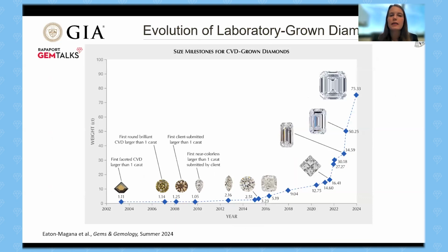Now, in the past couple of decades, there's been a huge evolution in the quality and the sizes and the quantity of laboratory-grown diamonds. So here we have an example of the CVD-grown diamonds. And back in the early 2000s, most of the material was really brown, small, not necessarily the most valuable within the gem trade. But as they have perfected their growth procedures, they have also introduced post-growth treatments. We have seen a huge increase in both the size and the quality, with the largest ones reaching now about 75 carats inside, faceted. And in this diagram, I just want to highlight the fact that GIA publishes materials in a range of different sources, including Gems and Gemology, and this is from a big review article that we released this past summer.